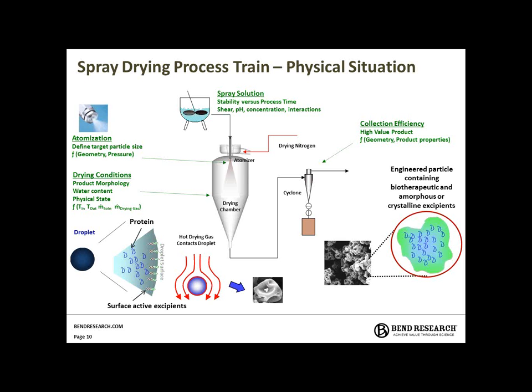As mentioned earlier, a lot of the tuning handles here can really define the product morphology, the water content, or the physical state. As an example, in the cartoon in the lower left-hand corner, linking the formulation and process, we're showing a problem statement we see occasionally of purposely trying to impede the protein from the surface of the droplet and ensuing particle due to stability reasons. So here we have a surface active excipient, a formulation decision, and linked to that, we might purposely dry under colder, wetter, slower conditions to allow the surface active excipient to have higher mobility for a longer period of time and migrate its way to the surface for these stability reasons.